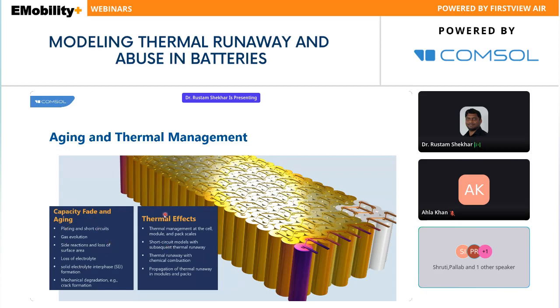When it comes to thermal management, which is one more cause of the failure of the battery, you can perform the thermal management at the module and the pack level model, where we can incorporate the short circuit, which can be internal or external, and thermal runaway. So there is a violent chemical reaction that may happen after failure. So the thermal runaway or thermal behavior after the failure due to the chemical combustion can be incorporated, and then you can see the propagation in the pack, which covers starting from cell level to see the abuse modeling, and then the propagation part into the thermal management.